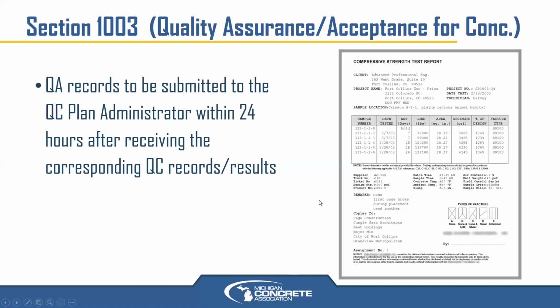And again, the break results, like you see an example of here at 28 days, those need to be submitted within 24 hours of when they are generated. So not just the fresh concrete, but also the hardened concrete results. So that is new for those of you on the QA agency, consulting for agencies side. You may have already been doing that, which is good practice. And it depends on where you go, whether there are folks that choose to do that. But now it is required within 24 hours.